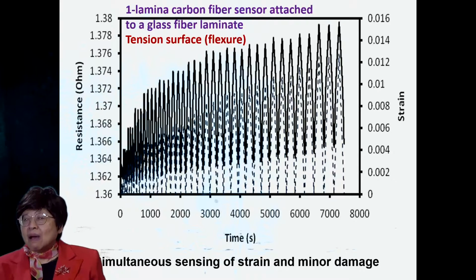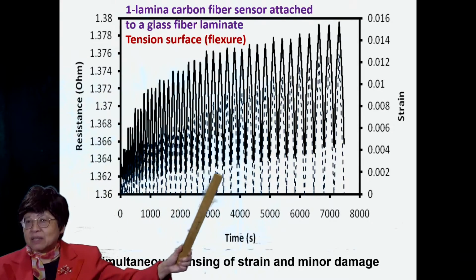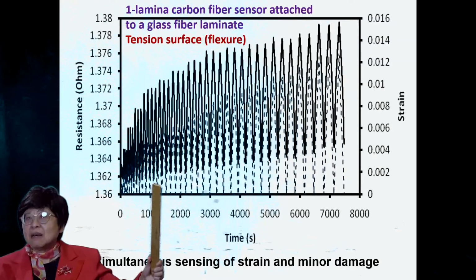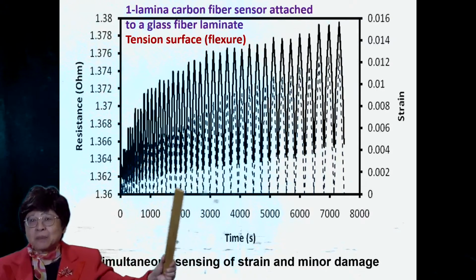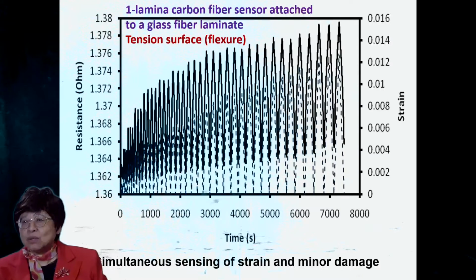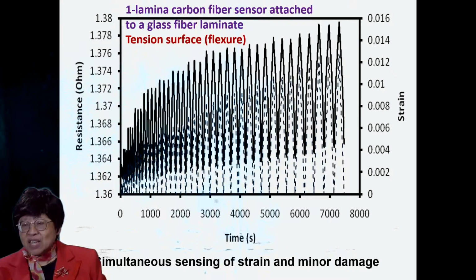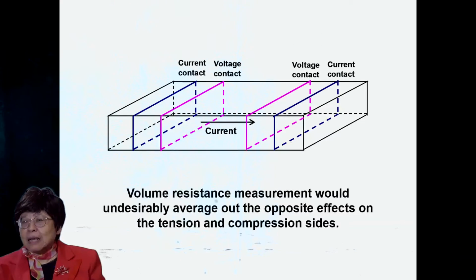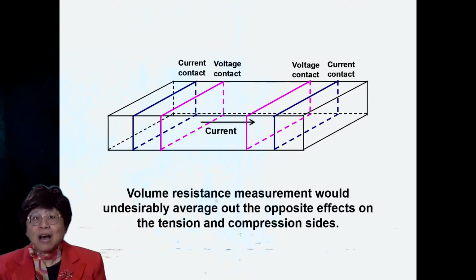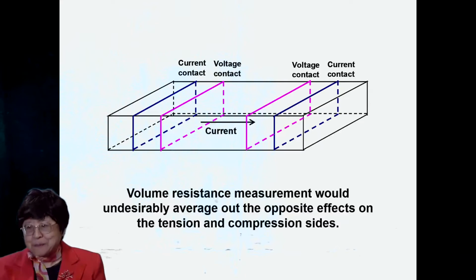In one scenario, we can have the baseline resistance of the tension side surface resistance climbing up cycle by cycle, and that is due to minor damage. So one can actually see the strain effect and the damage effect simultaneously. Now, if one, instead of measuring the surface resistance, measures the volume resistance, it would not be very wise, because the volume resistance gives you kind of the two opposite effects on the two sides averaged out. So it wouldn't be very suitable at all.